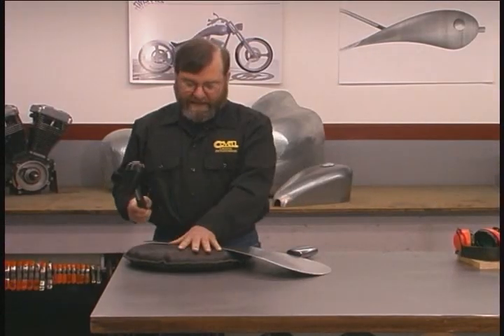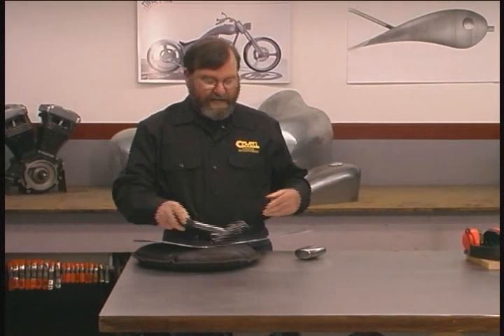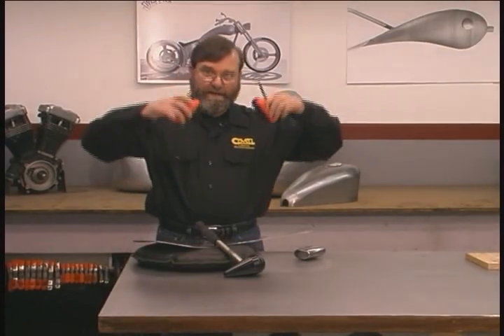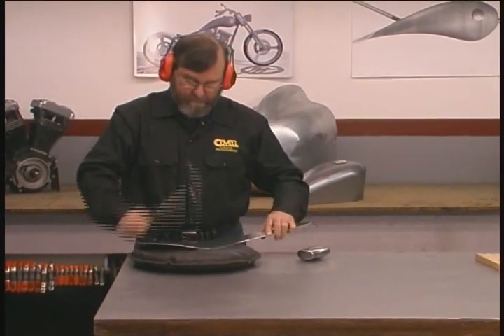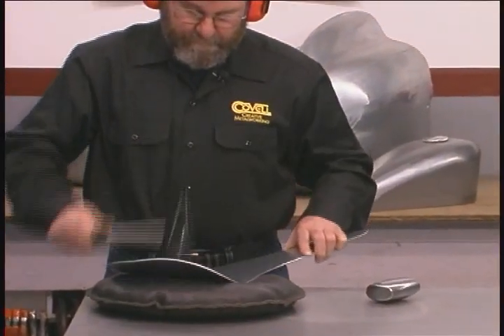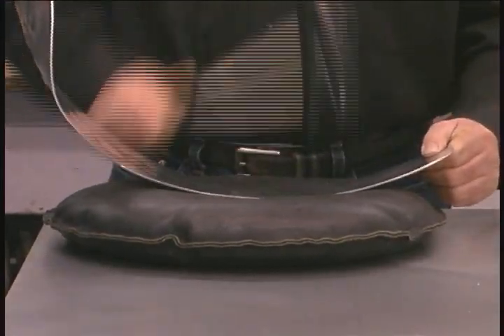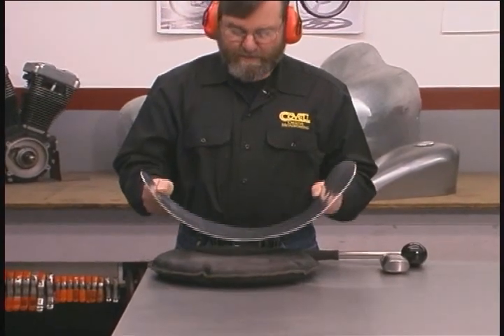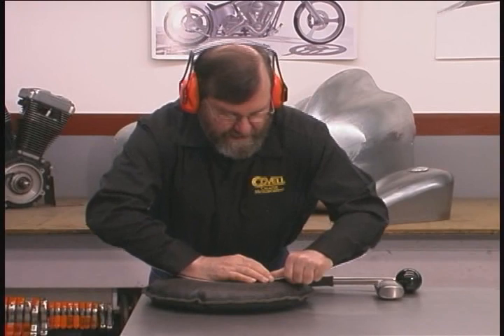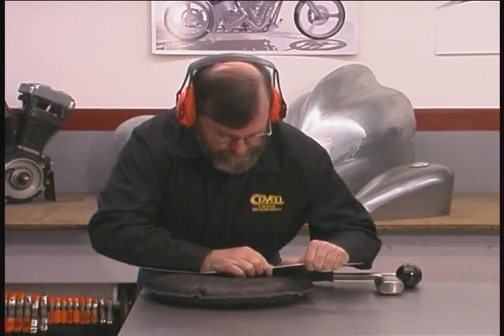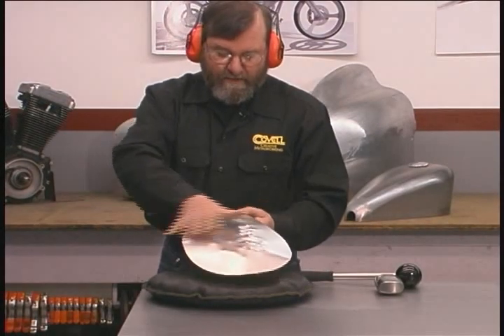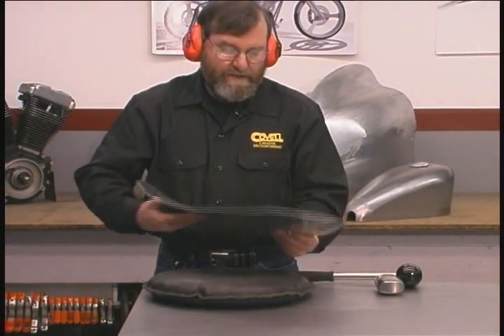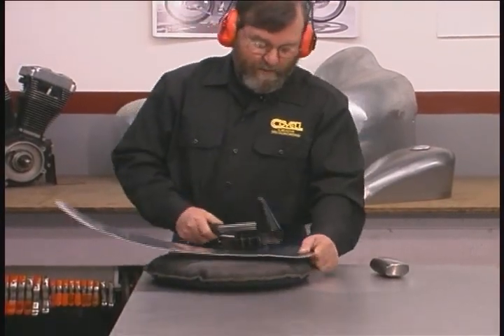We'll be working with a mallet and a sandbag. And basically we just place the metal on top of the bag and work into the bag with the mallet until we get a shape like what we want. So there's the result of our first round of hammering. You'll see that the part has taken on quite a cup shape, much more so than we want from front to back. So I'll use my elbows to help push the ends of the tank back where we want them. And now we can gauge how much doming we've achieved. Very slight, so we'll continue with the mallet and bag work until we have as much doming as we want.